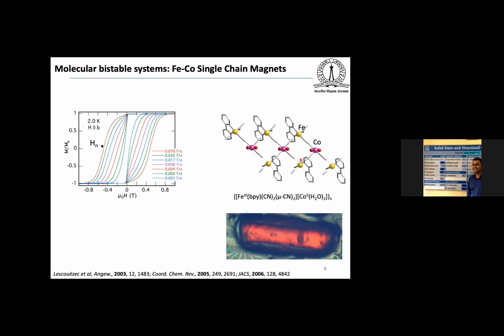Here you can see they have used iron BPCN2. This is the cyanide building block, and that is connected with the cobalt 2 systems, where the cobalt is four sides surrounded by the cyanide nitrogen, and 2 are occupied by the water molecule, oxygen from the water molecules. And here is the microscope image of the single crystals, and you can see the hysteresis is changing when you change the sweep rate. So this is the first example of iron cobalt single chain magnets.